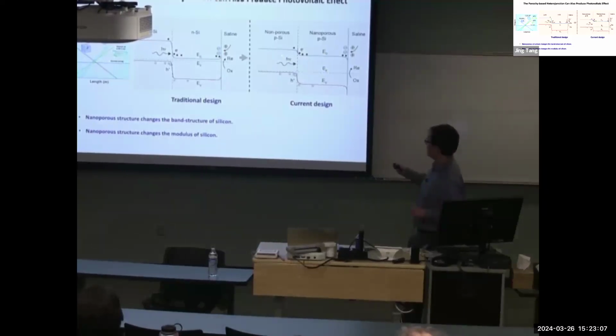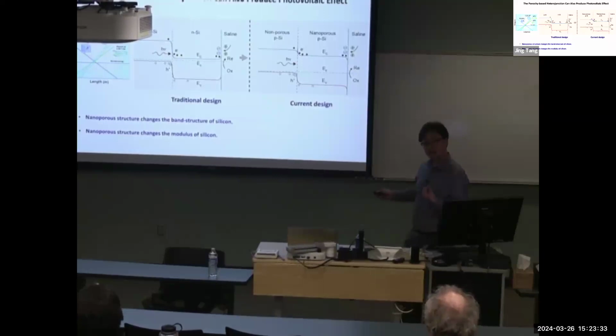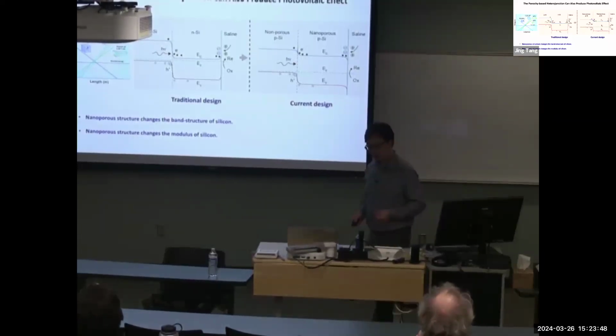When reaching equilibrium, those 2 layers, non-porous and nanoporous, form what we call a staggered type 2 heterojunction, which is quite similar to the traditional p-n junction, the building block for solar cell structures. So comparing those two structures, both can have a photovoltaic or photoelectrochemical effect, although we do not need to involve N-type doping. And the whole processing is significantly easier. We do not need a clean room or a very sophisticated environment for doping or microfabrication. The etching takes 10 seconds, no more than 1 minute. You can achieve this, and you just use a commercially available silicon wafer.